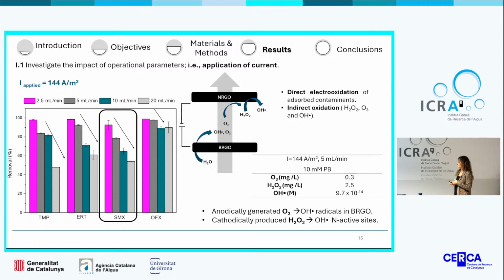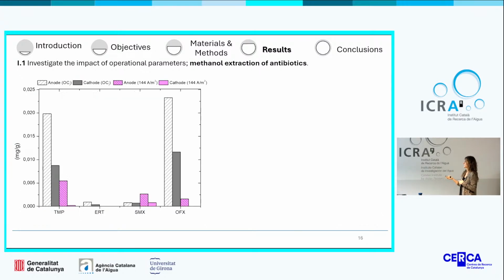Even though those antibiotics are not kinetically affected by ozone, it's important to mention that anodically generated ozone and also cathodically produced peroxide are actively transformed into hydroxyl radicals in the anode, and in case of the peroxide, in the N-active sites of the cathode. So therefore, it seems that all these oxidant species are actively participating in the electrochemical elimination of antibiotics, not only hydroxyl radicals.